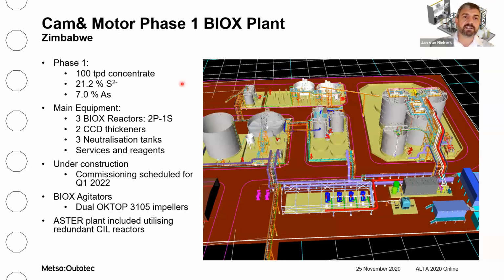The phase 1 plant will have a design capacity of 100 tonnes per day at 20% sulfur. However, when we did the design, we already designed the plant for the full capacity of 200 tonnes per day, with only a part of the plant installed during phase 1. So for phase 1, we will install only 3 of the 6 BIOX reactors, 2 of the CCD thickeners, and 3 of the neutralization tanks, as well as the associated services and reagent makeup. And this will give us sufficient capacity for the phase 1 operation. Phase 1 is currently under construction and commissioning is scheduled for early next year.